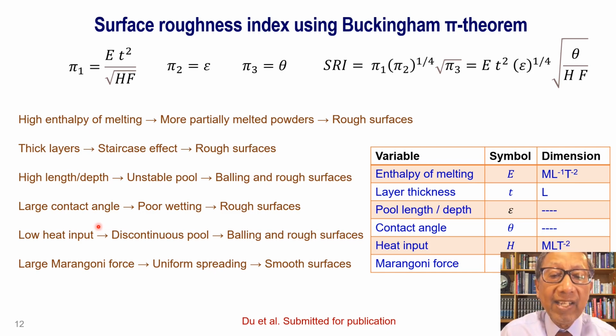Large contact angle will mean poor wetting, and therefore it can cause roughness. Low heat input may mean discontinuous pool, and the surface can be rough because of that. But Marangoni force, which distributes the liquid easily, if Marangoni force is large, then there will be uniform spreading of the liquid and the surface would be smoother.